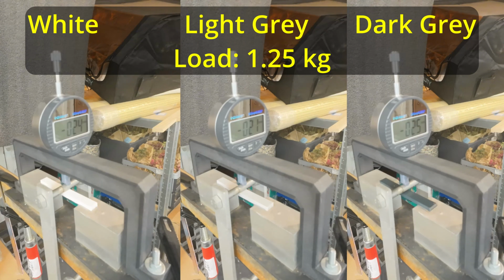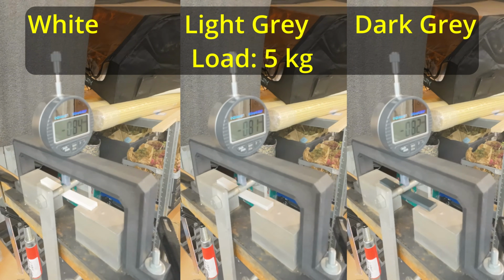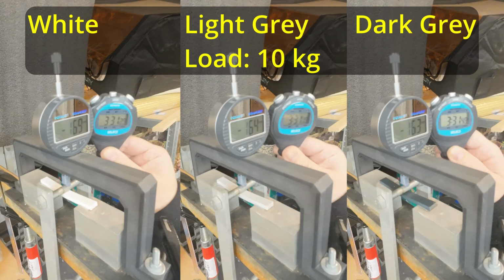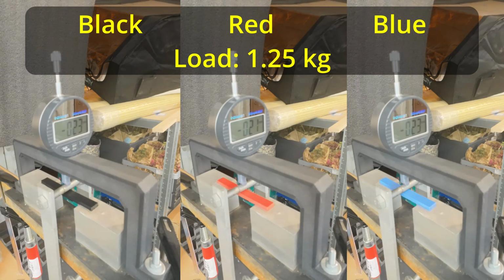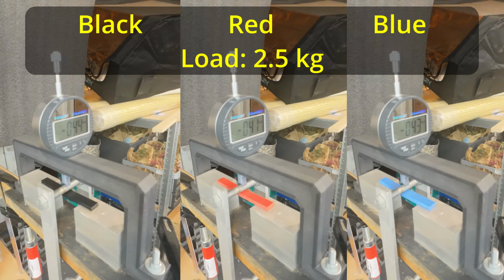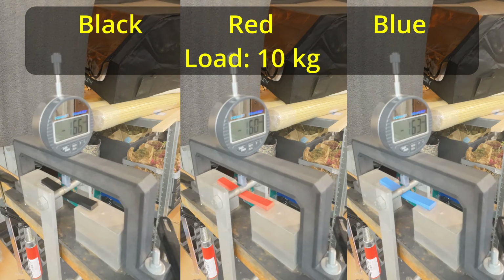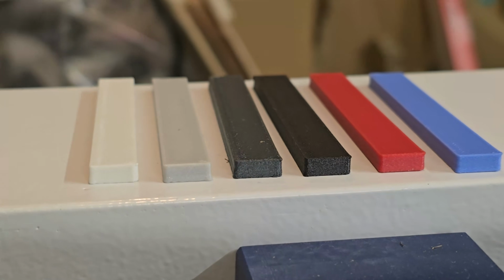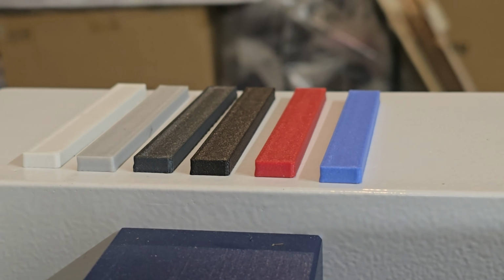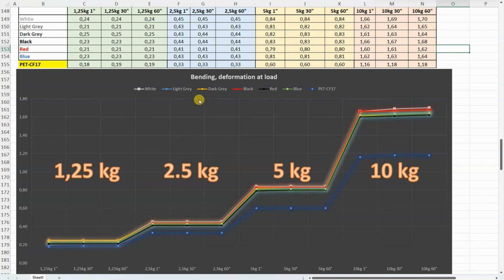3-point bending test. Distance between supports is 50 mm, first 3 colors, and I'm recording the deformation under these loads after 1, 30 and 60 seconds. These are the second 3 colors, last deformation under 10 kilograms, and visually there is no permanent deformation on any of them. I forgot to change the colors here, but basically they are very similar, no big difference. And these are good values, very minimal deformation. Even the additional deformation during that 1 minute under 10 kilograms is very minimal. But compared to the carbon fiber version, we can see more deformation on the glass fiber version.